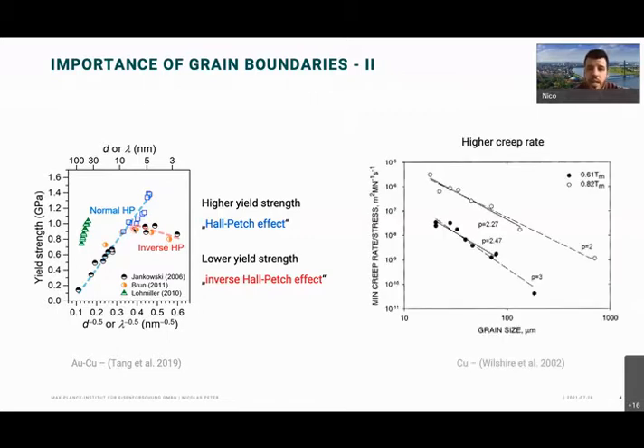Another example is the higher creep rate. If you, again, decrease the grain size, you also increase the creep rate, which might also have to do with grain boundaries. So there's a multitude of effects, and these are just some random ones related to grain boundaries, which make these defects quite important for our materials and how they behave.